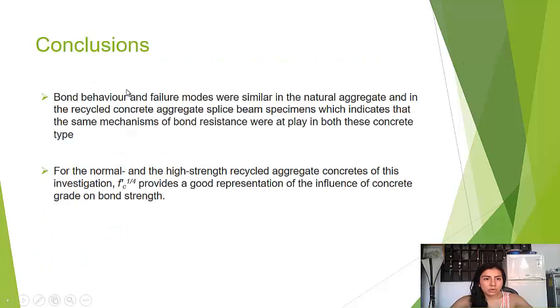As a conclusion, bond behavior and failure modes were similar in the natural aggregate and the recycled concrete aggregate splice beam specimens, which indicates that the same mechanics of bond resistance were at play in both these concrete types.